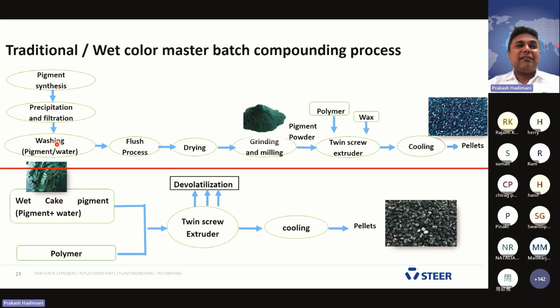But what we currently do traditionally is, after the washing, we flush. Once the flush process is done, we dry this. Again, we are putting in energy. I don't know how many hours we spend on this. Once the drying is done, we have to grind it into the required particle size. Grinding and milling has to be done. Later, the pigment, a polymer and a wax, we pre-blend or pre-mix in a high-speed mixer and put it in the twin screw extruder. Again, we have to apply more energy. Waxes, we have to use 10 to 15% of wax along with polymer to break the particles of the pigments.